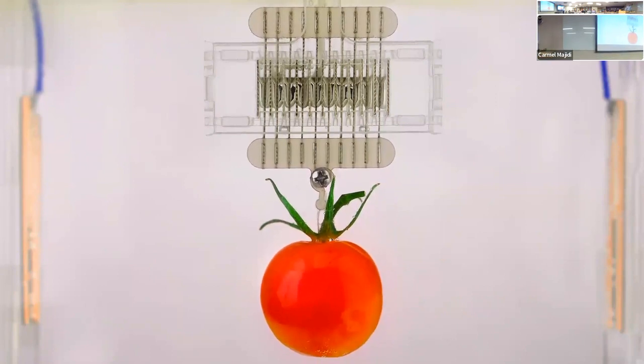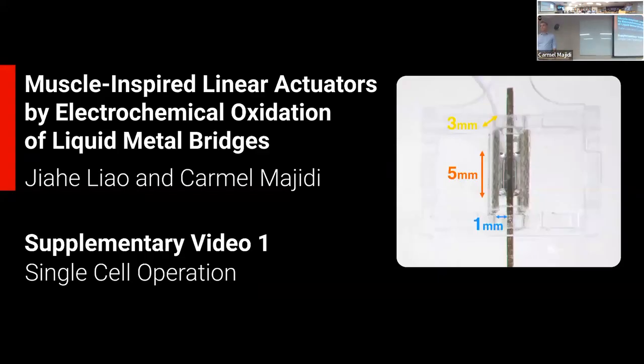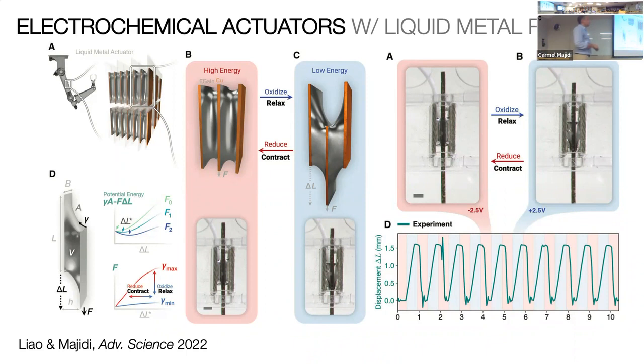And surface tension tends to go with not just area, but, well, I guess in this case it's area. So it would help further to have it parallelized, like lots of little bubbles. Yeah, if you go down to droplets, because it's the perimeter to volume ratio, the smaller we go, the larger those ratios are, so it definitely helps. In principle, if you got these down to a sub-millimeter scale, I mean, they're already quite small, but if you got them even smaller, then I think it could potentially be viable for some actuator applications.